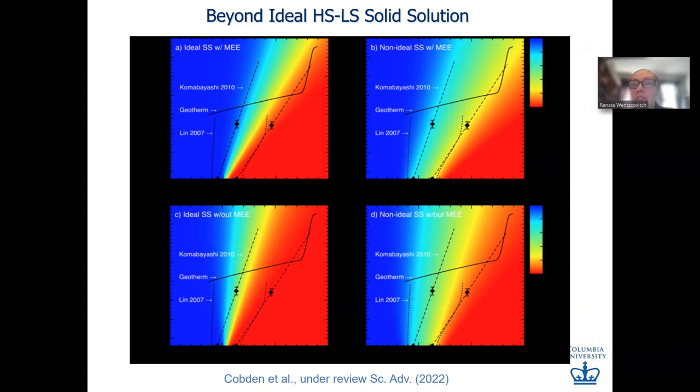Yes, that's what we did. Supercell calculations with iron in high spin, low spin state, all possible high spin, low spin configurations of that supercell with 18.75% iron at every volume. And I can show you how we calculate the excess free energy as well, but not here.